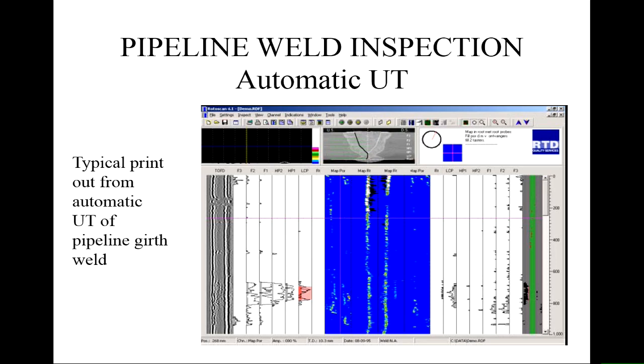So what you get from these systems is quite a lot of information here. You can see here roots, and then the hot pass, second hot pass, in this case filler passes, and you're looking for the signals coming higher than you were expecting, and you can see there's quite a lot of signal in this region here, and that's telling you that there's a lack of fusion defect within this material, and it does that for you in an automatic way. If you look at this case here, on this side, there's very little of that, so this is actually a good weld.